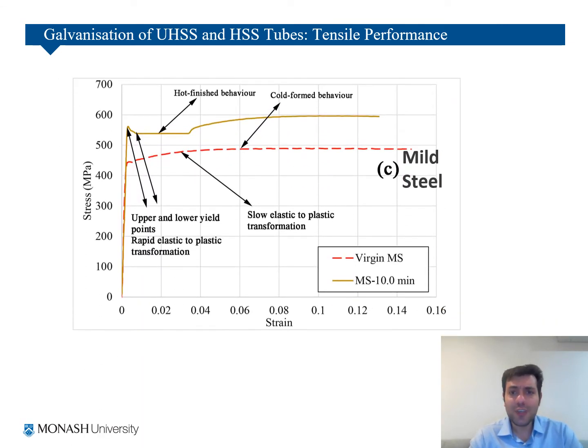Also, you can see in mild steel, opposite to those tubes, the yield and ultimate strengths are increasing, but the behavior again is changing from a cold form behavior to a hot finish behavior, where you can see the upper and lower yield points, a flat yield plateau, and then a strain hardening. But unlike those two curves, the ductility is decreasing.